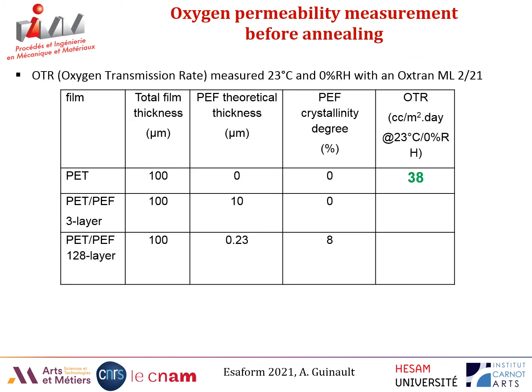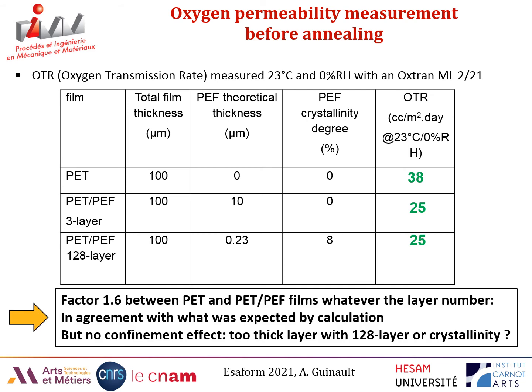Now we can look at the oxygen transmission rate, the permeability measurement. And what is interesting to see is that PET presents a value of around 38 cc per meter square per day. That is a classical value for amorphous PET. When you add PEF in the 3-layer and in the 128-layer film, the value is around 25. It decreased by a factor of around 1.6, whatever the layer number, and it is finally in agreement with what was expected by calculation by using the series laws for permeability. It's normal, but it means that as we do not have any effect with the 128-layer film, you don't have any effect of confinement.